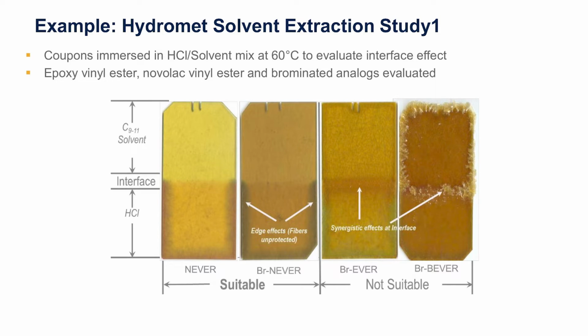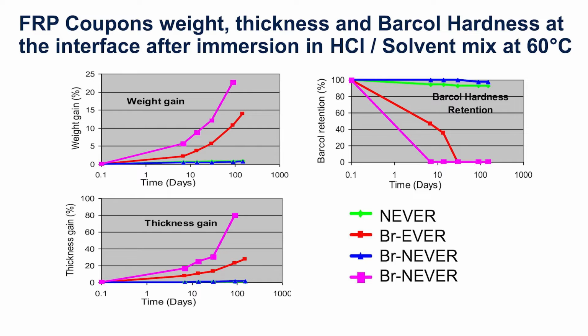Here's a great example, too, of something that's kind of unique. So this is a solvent extraction study that we did for the Goro Nickel project, starting way back in the early 2000s. And so in that extraction process, you have aqueous and you have solvent chemical environments combined in one application. And the goal there is to try to dissolve your metal salts in the water, and then use a chelating agent that can be extracted by the solvent to pull the metal out of the water into the solvent, purifying it from all the other materials that came along from the extraction process. And so what we have here, so we have the hydrochloric acid, and then we have the solvent layer, and then you have this interface.